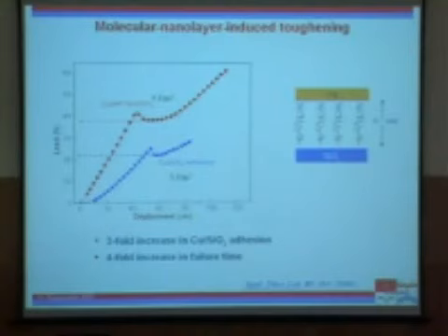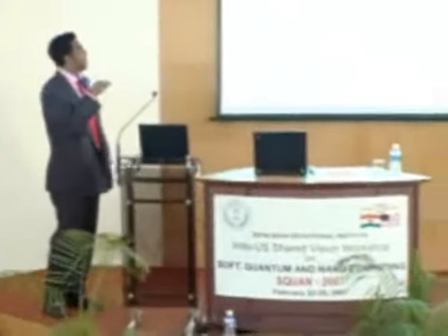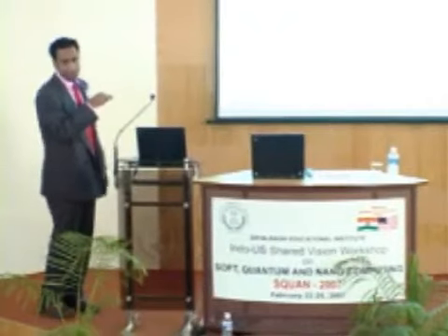To tell you what these numbers mean, in an Intel chip, a Pentium chip maybe, I don't know what the latest chip is called, typically for an interface to be considered stable in the chip, the value that you need to meet is about 5 joules per meter squared. So without optimizing, and using a single layer, we have actually tripled the value, right?